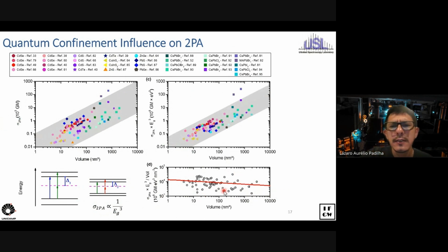And another thing that's quite interesting is that if you just look at these reddish points here, corresponding to the cadmium selenide, all this dispersion actually becomes much narrower. It goes in this distribution here. On the other hand, if you look at perovskites, even though they are basically the same material and basically the same size, you get more than 2 orders of magnitude spread. Look at this, for example.